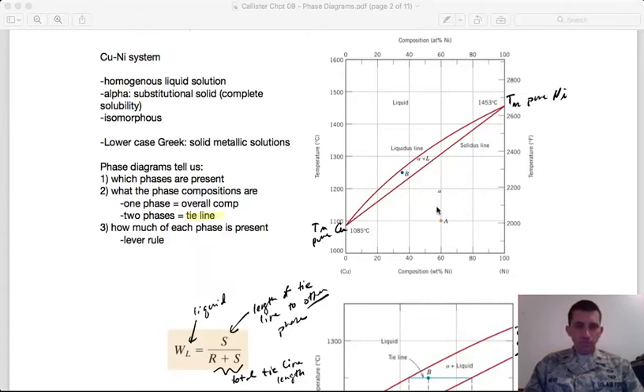So generally we give solid solutions or phases lowercase Greek letters, and so if you have one phase, generally that would be alpha. And so here we see that at a low enough temperature, we're going to have a solid, right? We're not melting at lower temperatures, so we're going to have this solid phase here, alpha, and there is a boundary between this solid alpha phase and the liquid and alpha region. And this boundary is called the solidus, right? Which makes sense. It's the boundary between solid and anything that has a liquid component. And so then you have this narrow region where you can have solid and liquid coexisting, and then if you go up and higher in temperature, you will cross the liquidus line. This is the line that, like you would expect, separates the liquid from things that have any solid component.